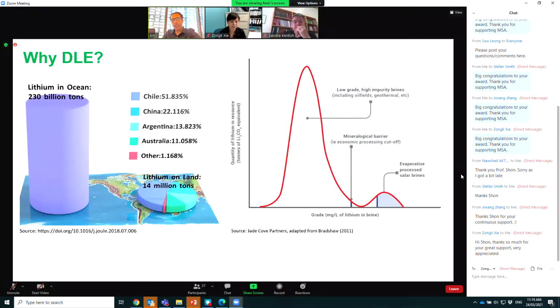The other interesting thing that you might want to know is that the amount of lithium in other resources, such as seawater, is significantly larger than on the land. In oceans, we have 230 billion tons of lithium compounds, whereas on the land, somewhere around 14 million. And this is very important.